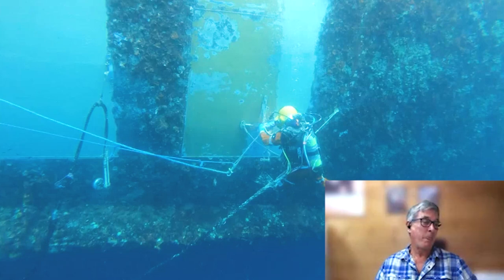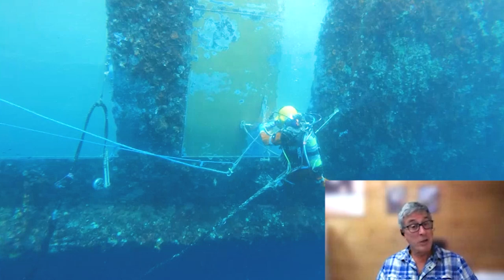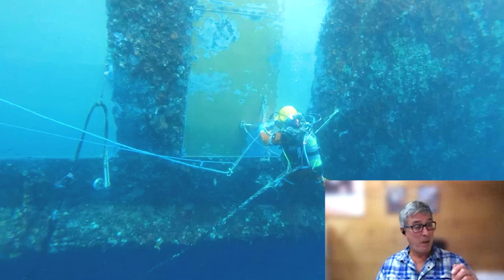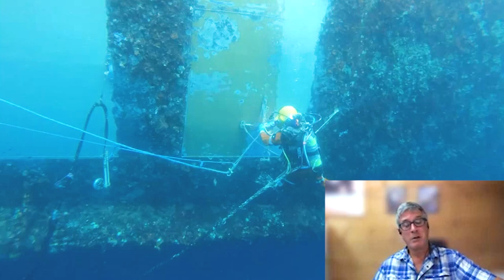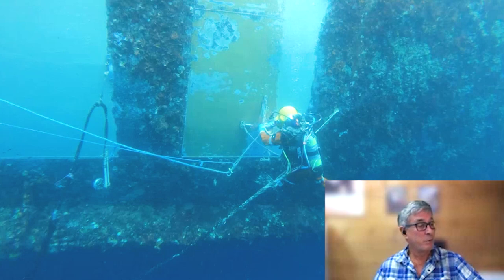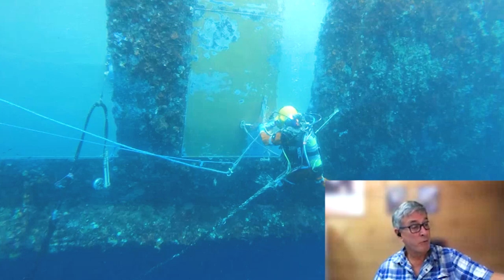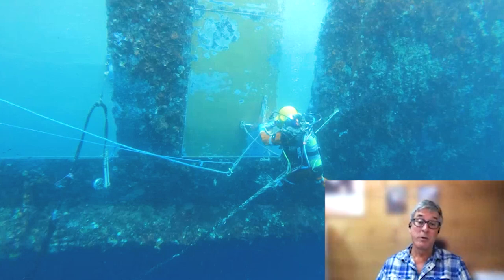uses his training and applies the coating correctly, we regularly use a wet comb thickness gauge to check the coating thickness. But with practice, after you've done that 10 or 20 times in your painting over an area like this, you know that you're going to have 250 to 300 microns of coating over the existing coating, which is well more than what was there in the first place.